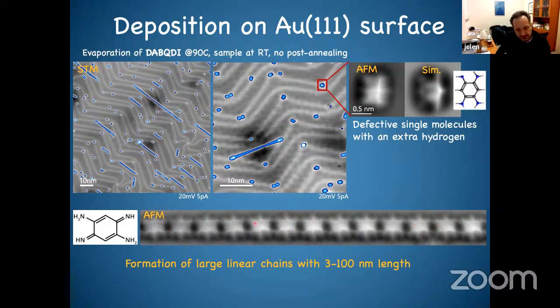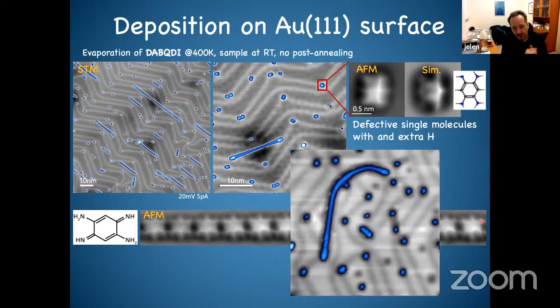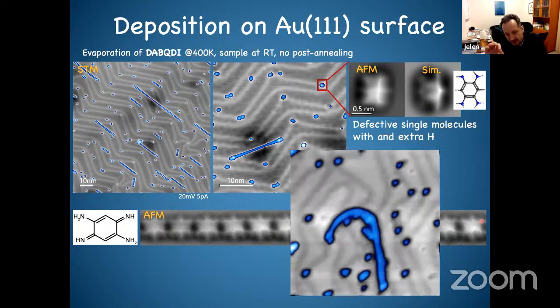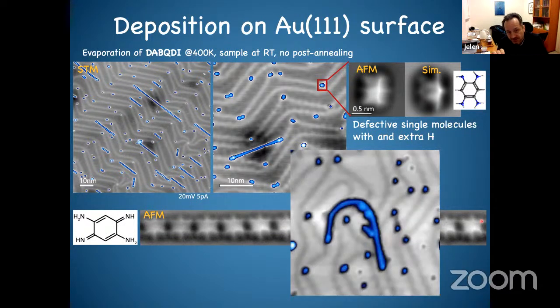Now when we take the CO tip, these chains could be up to 100 nanometers, and you see they are perfectly symmetric. So then you reveal the chemical structure of these molecules. What is more interesting is that now we can take a tip and we can move these chains, okay?